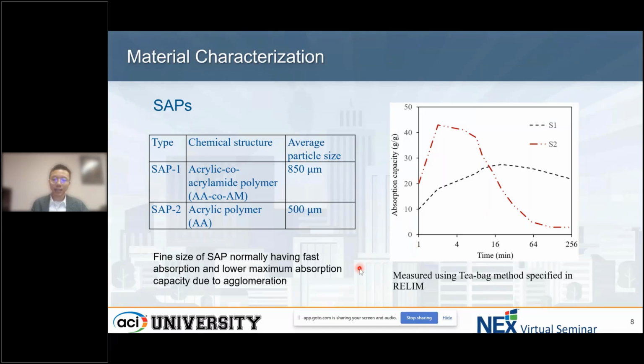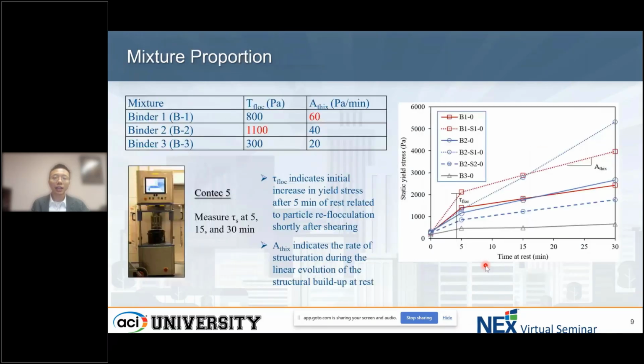And then we choose 3 different reference mixtures, and these reference mixtures are made without SAP. The reason why we choose these three reference mixtures is because they show different thixotropy. We determine the thixotropy using 2 parameters. We measure the static yield stress at 5, 15, and 30 minutes, and then we determine the first parameter called